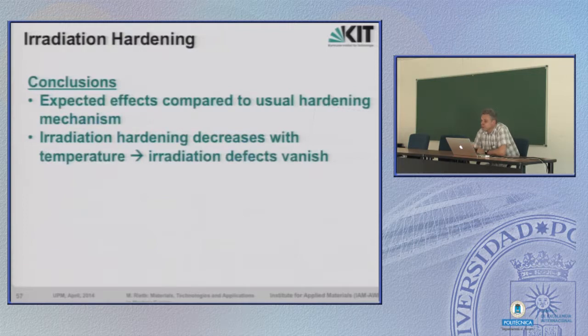Time for a conclusion. The expected effects compared to usual hardening mechanisms are the same, because you can only harden a material by what you have. In this case, I have given you a few more ingredients by irradiation, but the effects are the same. Dislocations cannot so easily glide anymore compared to a perfect lattice, and this is what makes the material harder and stronger. Irradiation hardening decreases with temperature, and in practical terms, this means, for example, for 9 chromium steels, if you irradiate them at 400 centigrade or even higher, then the irradiation hardening doesn't take place, or at least at a very low level. So this would be a very good operating regime for such materials if you want to use them in nuclear applications.